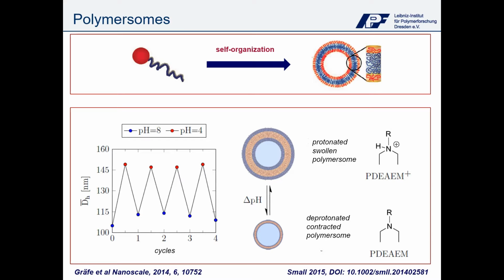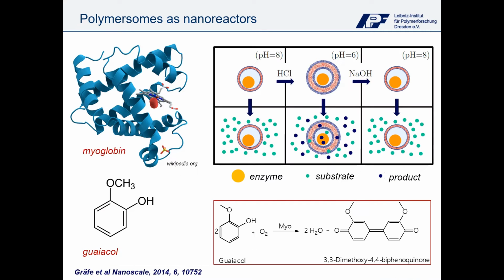First example is based on polymersomes, which are vesicles based on components similar to liposomes, which have hydrophobic and hydrophilic parts. In this particular case, we have copolymers with hydrophobic and hydrophilic parts, which can self-assemble, building polymersome vesicles. These polymers are cross-linked, so that depending on the pH value, they can shrink or open their membrane, allowing penetration of small guest molecules.